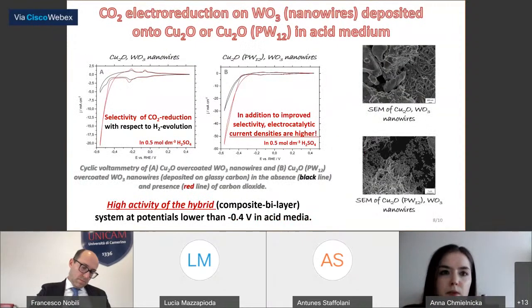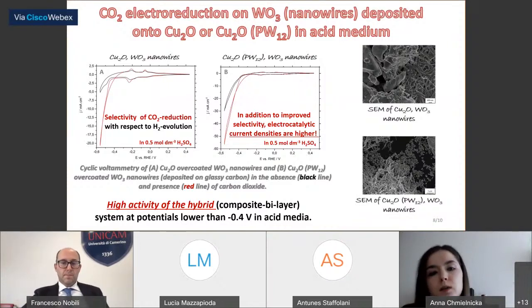On this slide, we have CO2 electroreduction on tungsten oxide nanowires deposited onto copper-1 oxide or modified copper-1 oxide. In figure A, we see selectivity of CO2 reduction with respect to hydrogen evolution. In B, in addition to improved selectivity, electrocatalytic current densities are higher. In both graphs, we have typical tungsten oxide peaks, and we have a high activity of the hybrid system at potentials lower than -0.4 volt in acid media.